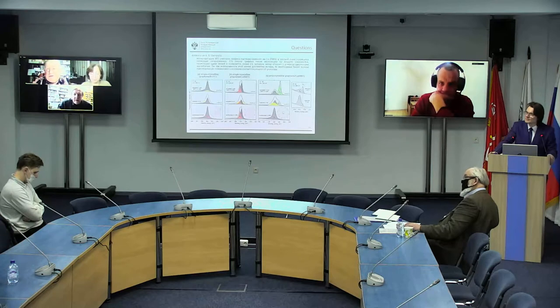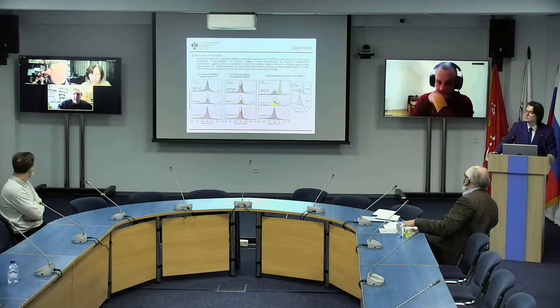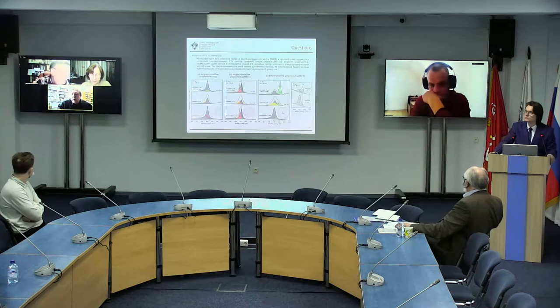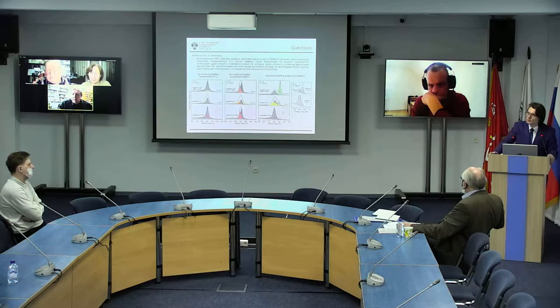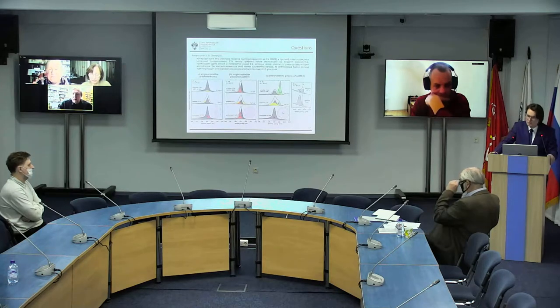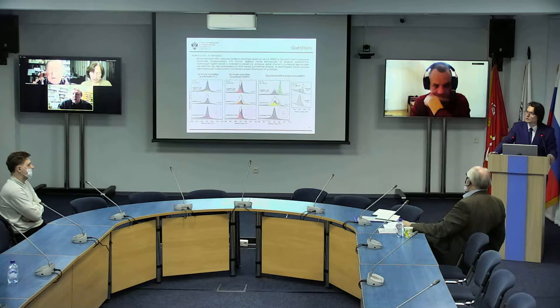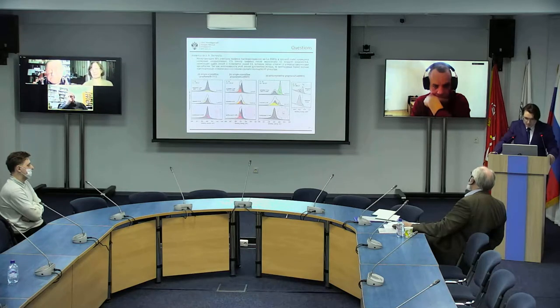Okay. I still have a question left. On the interpretation of C1 peak. So you associate it with the presence of oxygen. So that's carbon that interacts with oxygen adsorbed on the substrate, because the presence of oxygen usually leads to a shift to higher binding energies, and here we see a shift to a lower binding energy. Can you explain this? Yes, I'll give it a try.